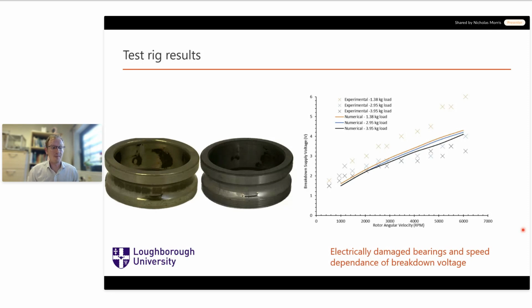And it's well established that dielectric strength, when you measure it at different electrode distances, changes significantly. So it wasn't unexpected, but we wouldn't be able to use the standard value for dielectric strength of this fluid. But it's an interesting finding, nonetheless, to show that to fit this data, we had to use a significantly higher dielectric strength for the lubricants.